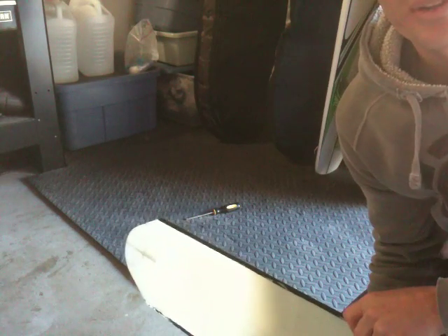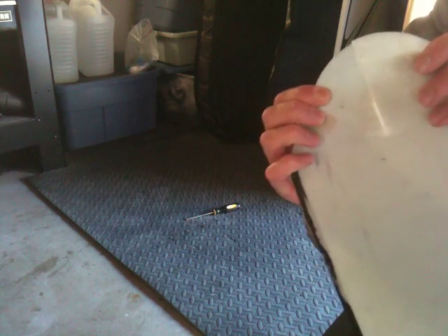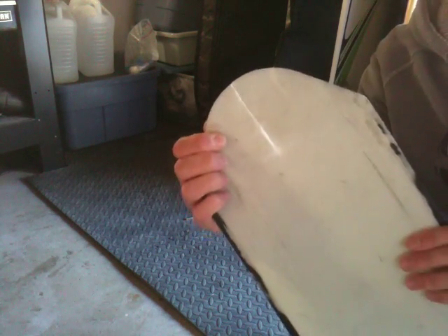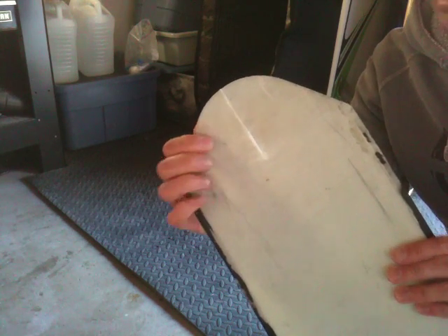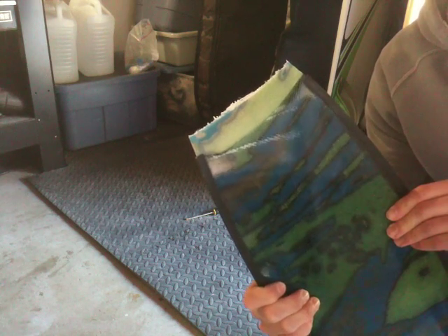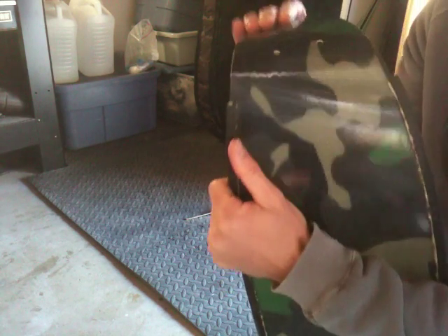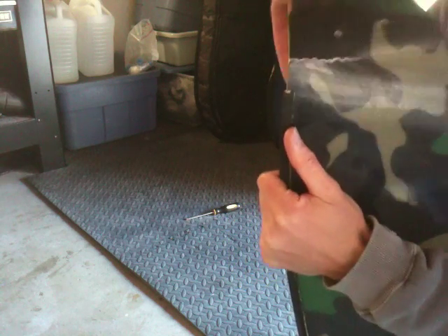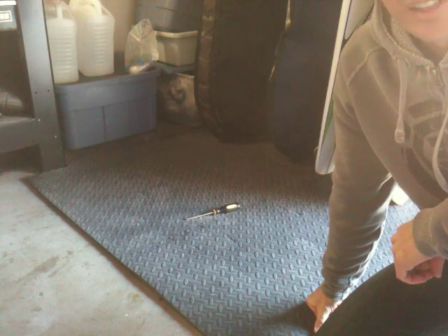Hello and welcome to Moana Waterman's Garage. This is an example of how a typical fiberglass blade cuts, rips, or breaks — often along the zero degree axis. Another common place is along the 90 degree axis. You can see this white line here where this fin is broken at the 90 degree axis. That's typical of a zero and 90 degree fiber orientation fin.